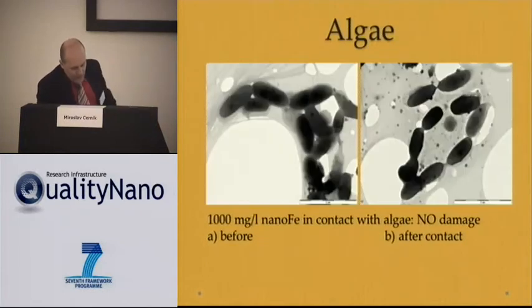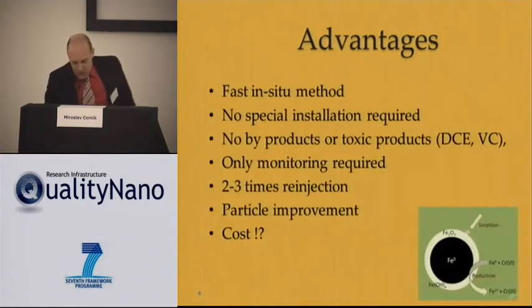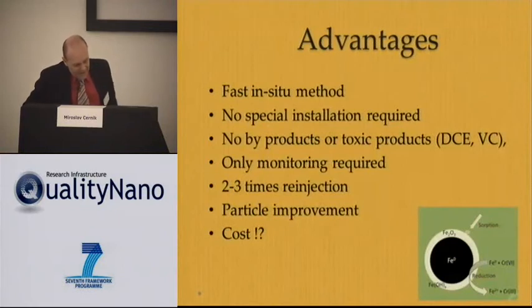surface water. If you look at the algae, there is no negative effect, no damage, so that for the bigger organisms, the effect of nano iron is not negative, so that it's good for the application in the field. So as a conclusion, I showed you some application of the nanomaterials for treatment, for cleaning of the environment. It's a relatively fast method which has no need for special installation, no byproducts or toxic products are generated. It needs only monitoring and 2 or 3 times re-injection to clean the site.